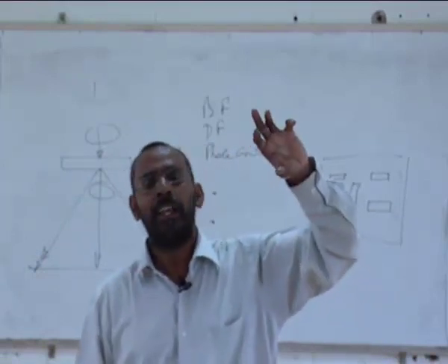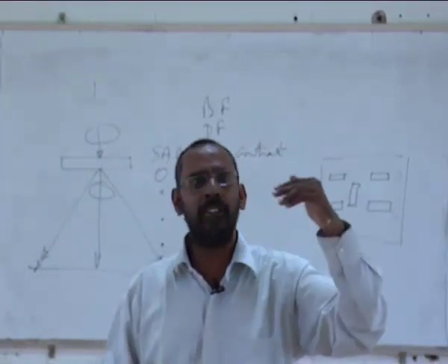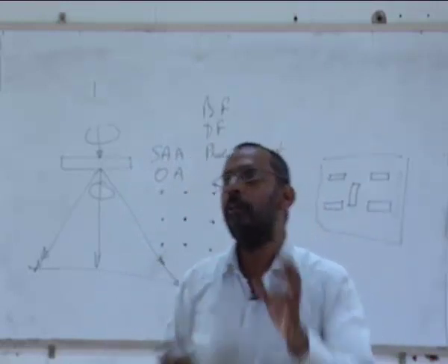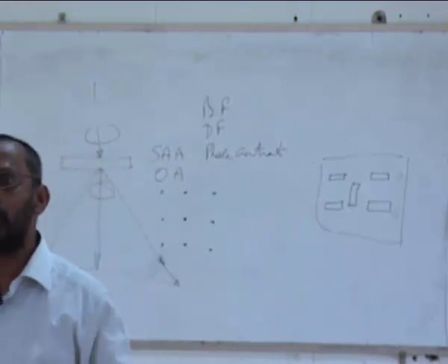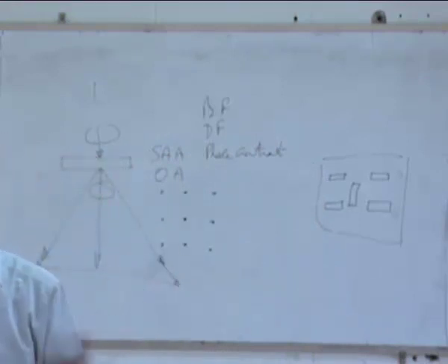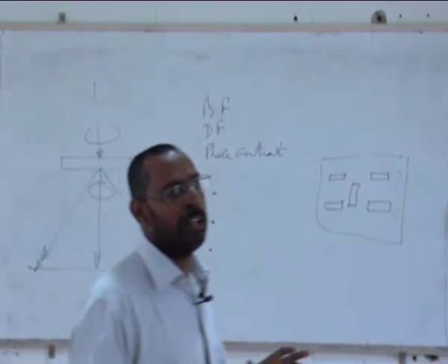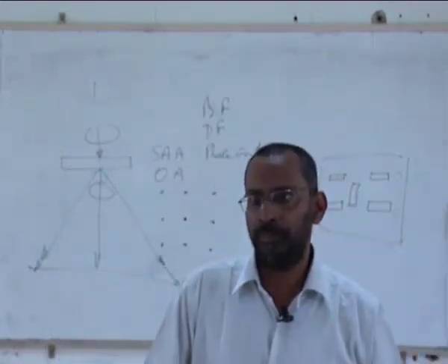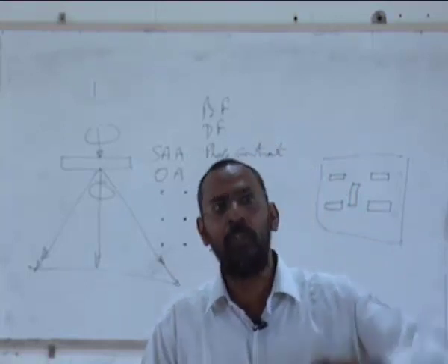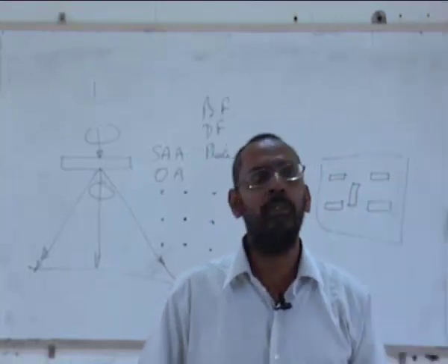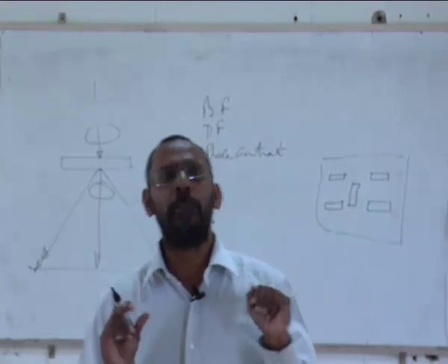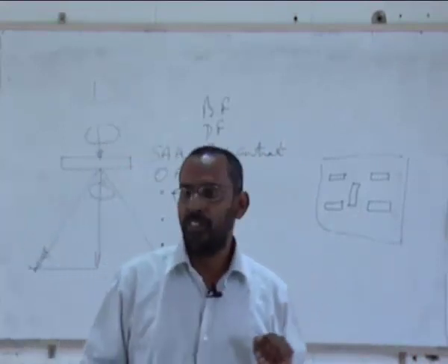If the strain energy between the particle and the matrix is very small, when will it be very small? When the misfit is very small, then the strain energy is very small, and when the strain energy is very small, then automatically the precipitate will be spherical. But if the misfit is very large, then the system will try to choose that particular precipitate shape which will have a minimum strain energy, and that one is the disk.